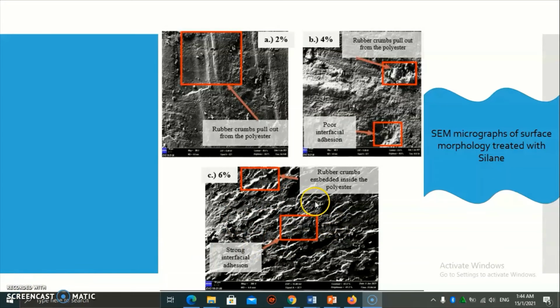For the 6% silane treatment, the rubber and polyester were really embedded in each other, and there is no crack, void, or damage, which was better than the other two concentrations. So it means that the more silane solution we use, the stronger the interfacial adhesion will be.